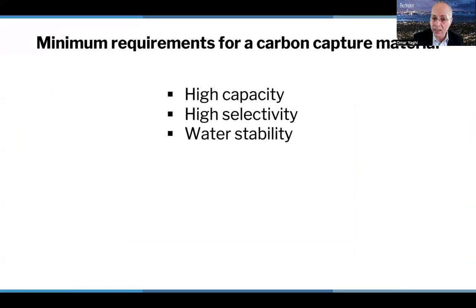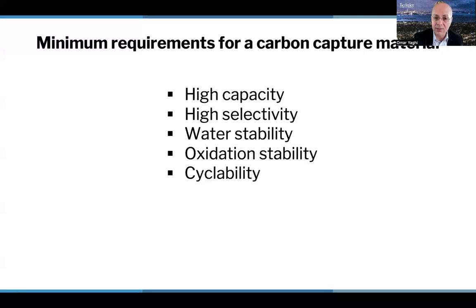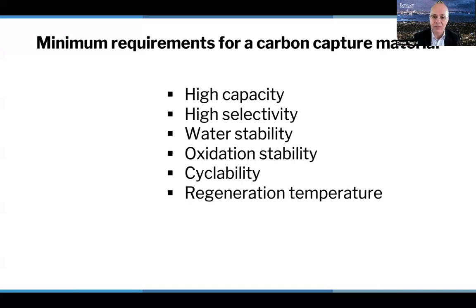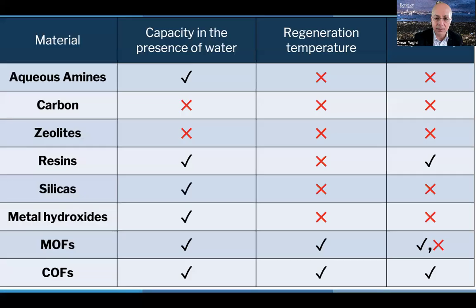They need to be water stable. They need to be oxidatively stable, and they need to be cyclable. They also, once you bring in the CO2 or water into the pores, you need to regenerate the material without having to heat it up to very high temperatures. So the lower the temperature of regeneration, the better off you're going to be, because the lower energy the system is going to require. And it needs to be scalable. So this is a tall order for materials, but it's not beyond the reach of reticular chemistry.